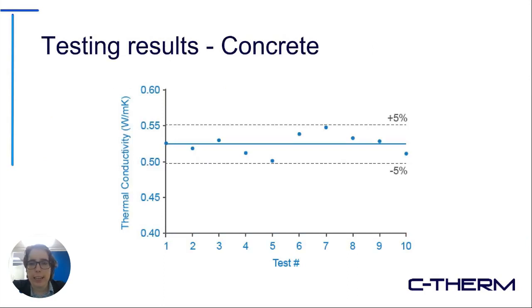So this is looking at 10 different locations in the same sample material, and you can see that the spread of the data is quite tight for a concrete material. This is quite a self-consistent type of concrete. The relative standard deviation of this data was about 3%.